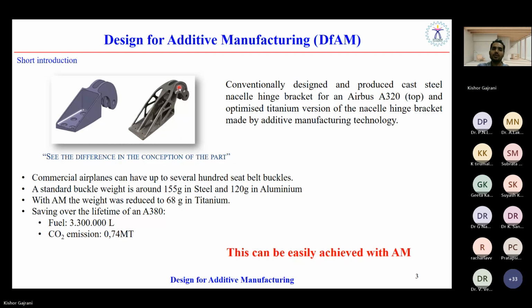Now, with steel, this component is in the range of 155 gram, and with aluminum it's in the range of 120 gram. But when you make it with titanium with the help of additive manufacturing with SLS process, the component is somewhere in the range of 68 gram. So more than half of the weight is reduced, particularly by changing the manufacturing way of a component.